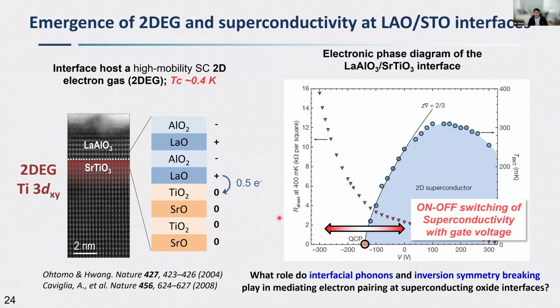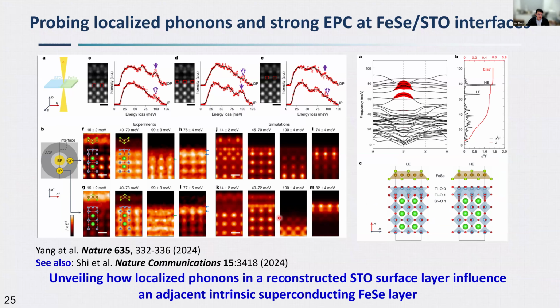interface. So if we look back to the literature, last year there were two very important papers, one published by Professor Xiaoqing Pan's group at UC Irvine, and the other, almost at the same time, published by Professor Peng Gao at Peking University. Both papers deal with a superconductor interface, monolayer iron selenide growing, again, on STO. But in this system, the STO layer reconstructs at the interface, and this correlates with enhanced TC in the iron selenide layer.